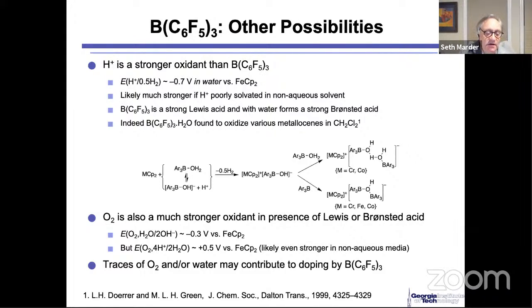And in this particular case, the literature is done by my former postdoc advisor at Oxford named Malcolm L.H. Green, who passed away last year. And he was an absolutely brilliant and one of the most creative chemists I've ever met. So he published a paper on the fact that when you work with these sandwich compounds that I referred to yesterday, and not even these very easily oxidized cases, but just regular sandwich compounds, if you react them with this perfluoroborane, you do in fact get oxidation products. And unlike the people working in organic electronics, okay, who mix stuff up and measure a conductivity, as an organometallic chemist, what he went and did was to isolate the products and actually structurally characterize them using X-ray crystallography, okay?